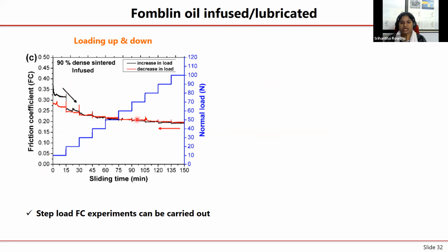And then the second test was done on a sister specimen. So for example, you can take a 90% aluminum oxide, fill the pores with the oil. Two samples you can take, same samples, sister specimens. One specimen is like when you are increasing the load. In the other sample, you are basically decreasing the load. That means you start with 100 Newton, later on you go with 90 Newton, etc.